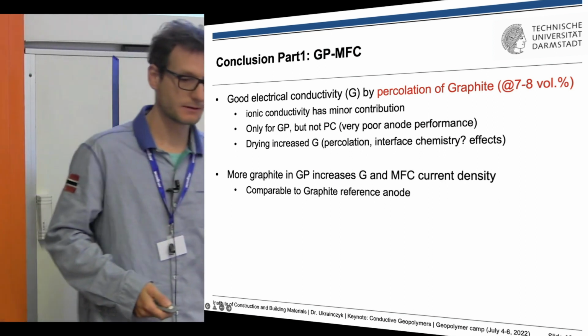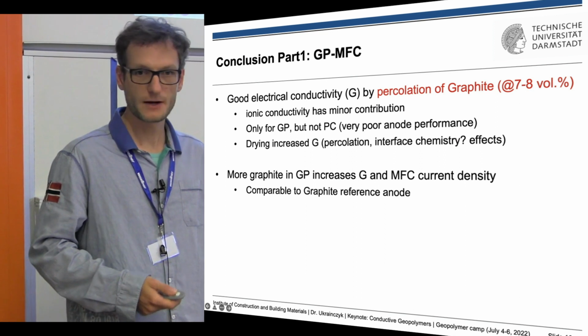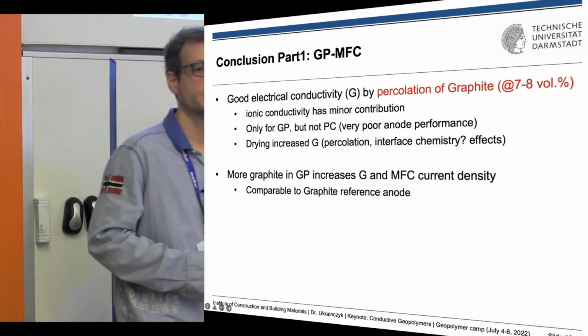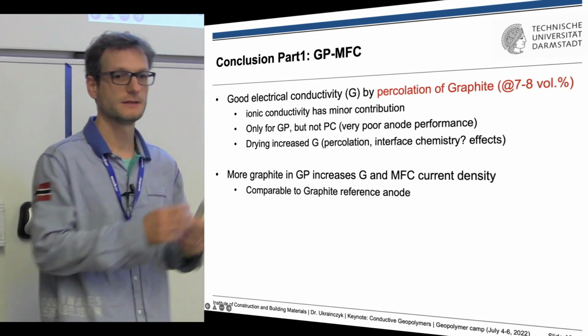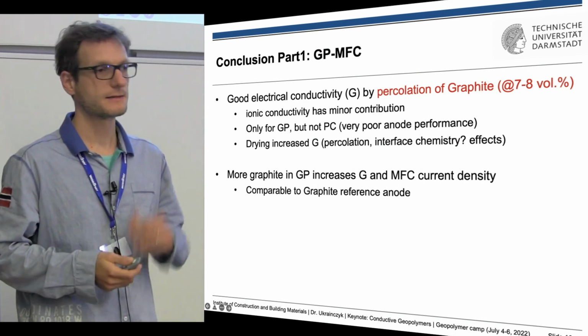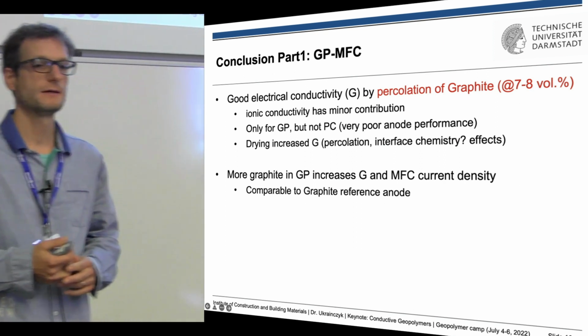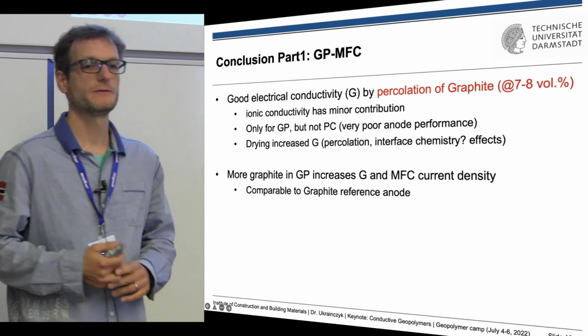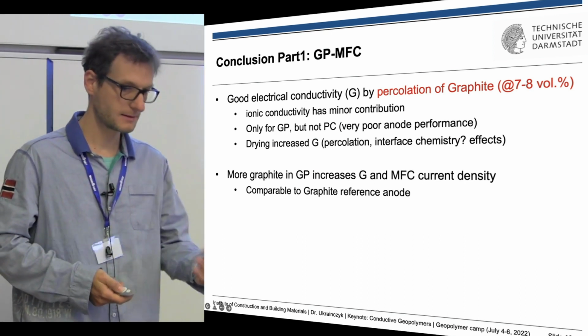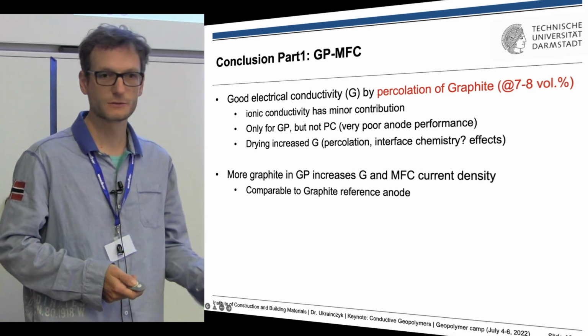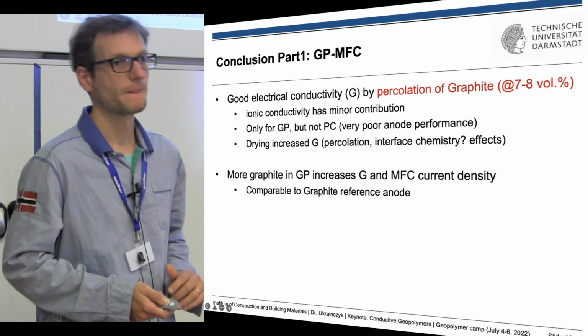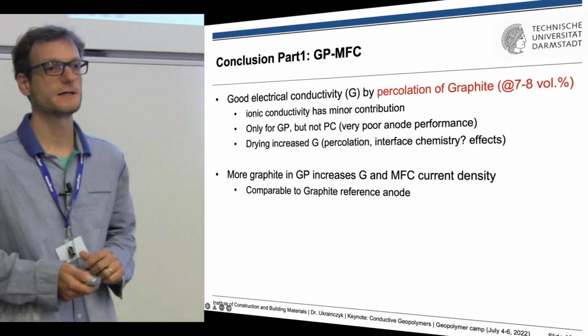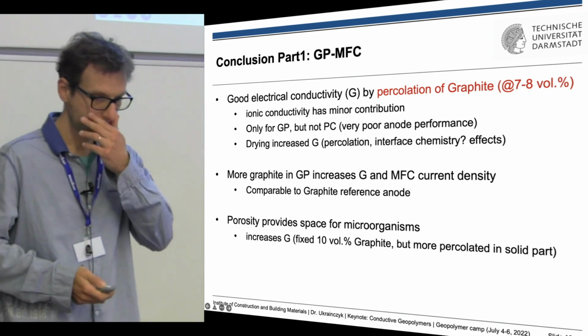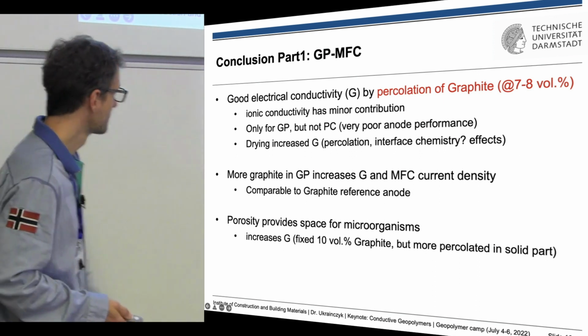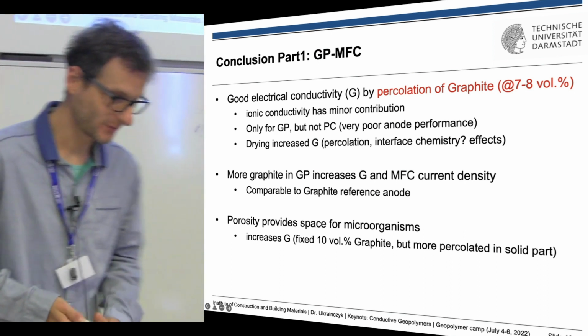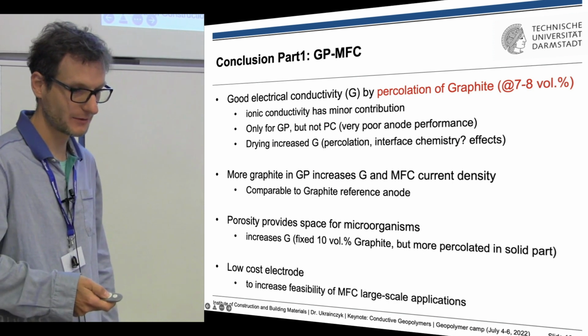We also got better current densities when we increase the graphite content, and also the porosity, which is also important. But the porosity is important for the biofilm, because for the bacteria we need a bigger accessible surface area, and the bacteria can better interact with the graphite if we have a porous material. So this is the idea, and this is how we also explain better current density. So it's not only the conductivity, it's also the availability, the accessible surface area of the anode. Yeah, the porosity, this is I think the key, how to tailor the porosity. I hope we have ideas how to go in this direction.